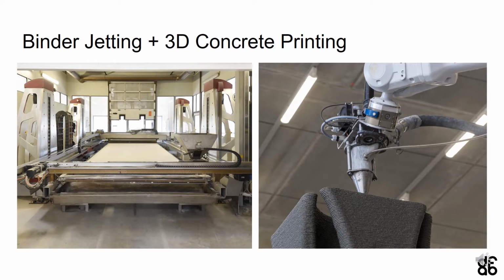The 3D printing process developed at ETH Zurich is based on a set-on-demand process that uses a Portland cement base mix and a calcium aluminate cement paste accelerator. By controlling the amount of accelerator dosed during processing, we can change the viscosity of our filament to create a continuous transition from digital casting to concrete extrusion printing.